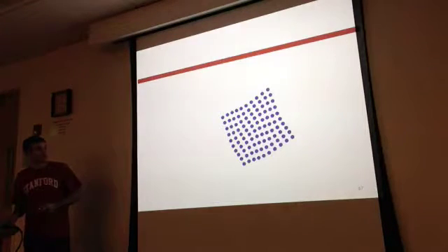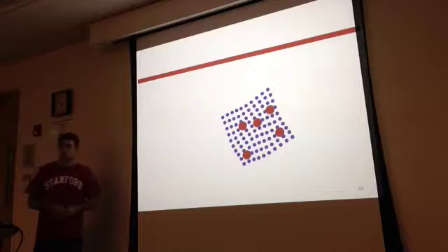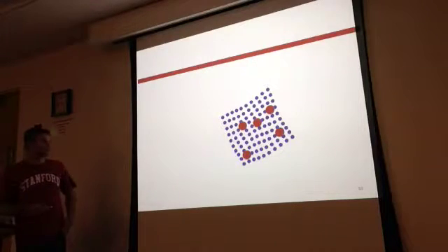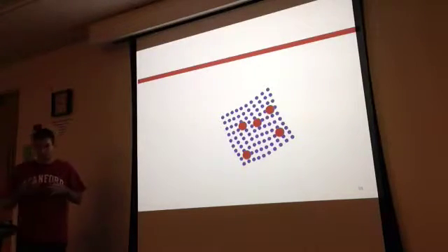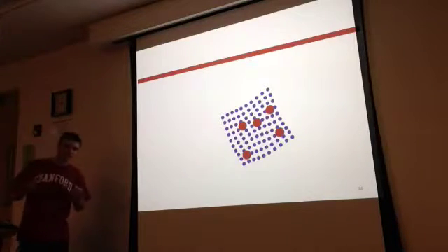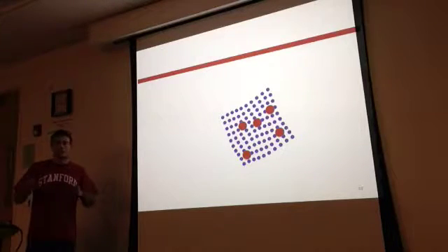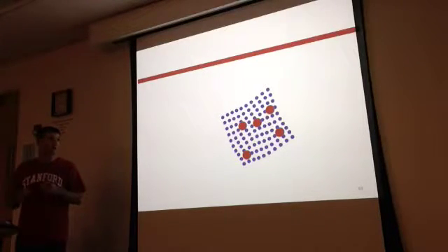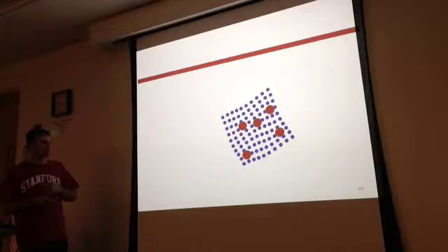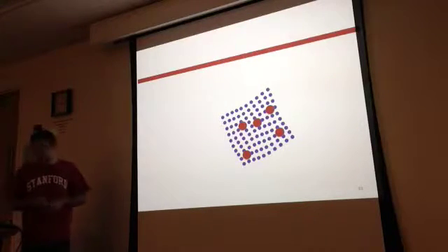Okay, so let's imagine we have some disorder in the crystal, some impurities or whatnot. In this case, you can imagine that these atoms interact with the laser light differently than do their blue neighbors. So if they absorb light more strongly, they might create some strain on a very localized scale. And then you can imagine that in this case, we're sort of pushing neighboring ions, separated by a unit cell or two, in opposite directions. So this might actually allow us to couple this long wavelength light to these short wavelength phonons.